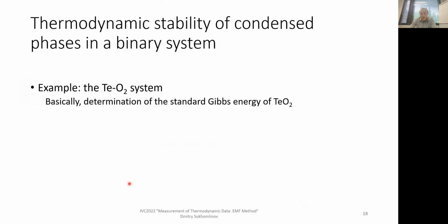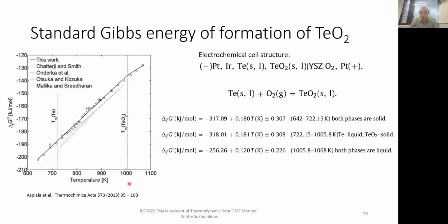Now we approach these showcases, and we start from a simple one. Thermodynamic stability of condensed phases in a binary system. We're going to look at the tellurium-oxygen binary system. In other words, we basically determine the standard Gibbs energy of formation of tellurium dioxide. The test electrode should be comprised of tellurium and tellurium oxide. And depending on temperature, both of them can be solid, both of them can be liquid, and then there is a range where the metal is liquid, but the oxide is solid.